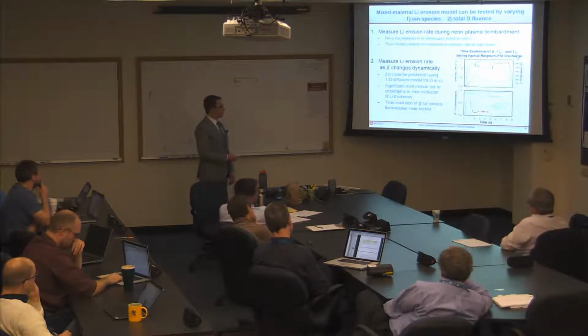And then I can plug those values of beta into the erosion rate predictions and see how it compares to the experiments. So this is what the predicted deuterium to lithium concentration would look like as a function of this time evolution of the deuterium flux and the lithium temperature that we measured. And I've plotted 3 different lithium coating thicknesses here, 25 microns, 50 microns, and 500. So 500 was the initial thickness, and then 50 and 25 are some nominal decreases. And so you get this sudden discontinuity at the lithium melting temperature, because as I mentioned earlier, the deuterium diffusivity tends to go up quite a lot once the lithium melts.